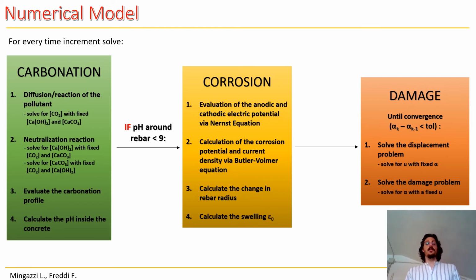So for every time increment, we first solve the carbonation problem, obtaining the carbonation profile and the value of the pH inside the concrete. If at any point around the rebar the pH is lower than 9, then we can solve for the corrosion process, obtaining the swelling associated with the rust formation around the rebar. And from the value of the swelling, we can move into the damage problem, obtaining the updated displacement and damage field associated with that swelling value.